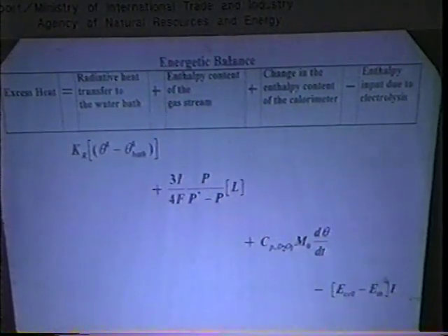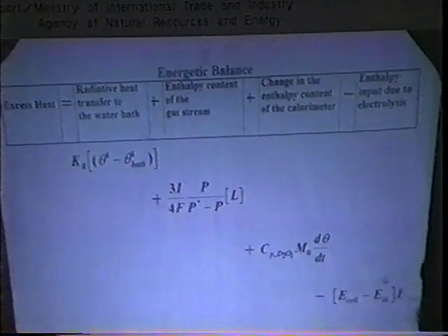So in that equation, we suppose that all losses are due to these numbers here. We don't assume there's anything else. There's no conductive losses. If there is any conductive losses, this should be seen in the calibration with platinum cathodes. Typical run is as follows. We work for some time at low current, like 0.2 amps. The temperature in that case is low, below 40 C. And then after 1 or 2 weeks, we raise the current to 0.5 amps, and the temperature goes up.